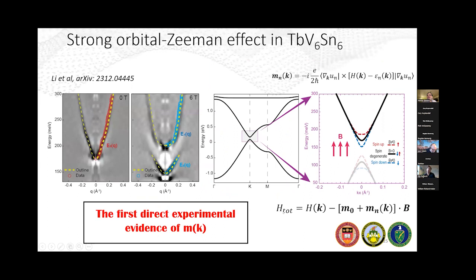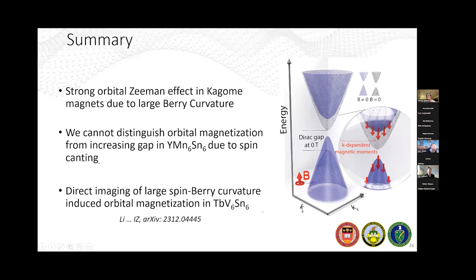So we can nicely attribute this, and we collaborate again with the same group of theorists, to a picture of these topological orbital moments that are most concentrated here at the bottom of the Dirac dispersion. The spin degenerate Dirac cone as a function of magnetic field splits into two different branches. You can even see, based on the shape of this one and that one, it looks like what you would expect from how the orbital magnetic moments would shift the bottom of the cone primarily, and then as you taper away from the K point, that effect tapers down. So this is the first, as far as we're aware, direct experimental evidence of these orbital magnetic moments with momentum resolution. This is something that's increasingly difficult for many other probes.